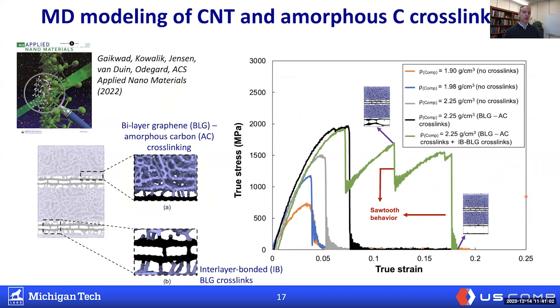And so this paper that was first authored by Prashik Gaikwad, this is essentially molecular dynamics modeling, trying to understand what's physically happening when we have amorphous carbon, we have the carbon nanotubes, and we're shooting it with gamma rays. So whereas the previous graph I showed you was more individual nanotubes and nanotube bundles, this was focused on what happens at the interface of amorphous carbon and nanotubes, because there's a lot of amorphous carbon in these carbon nanotube yarns.